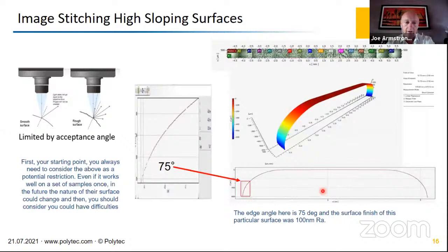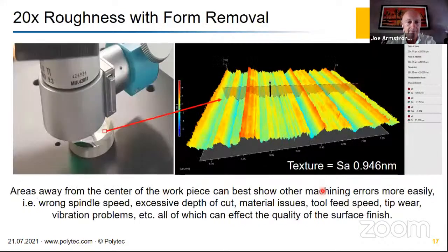Like I said, for surfaces that are compliant, even on surfaces that have some quite good surface finishes. Here I have an example of a surface that has a 100 nanometer Ra surface texture, and we're still able to measure maybe a slope of 75 degrees, providing that surface is offering the instrument some sort of micro nano scattering effect on the surface.